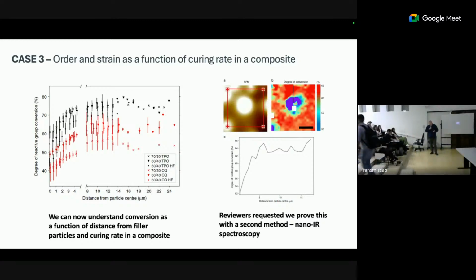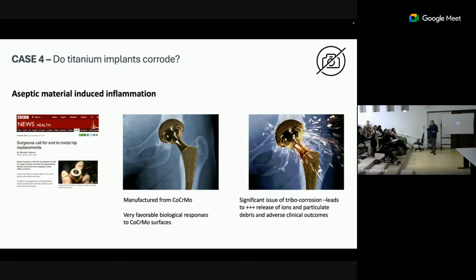On the right-hand side is a different type of measurement that the reviewers asked us to do, which is something that you don't necessarily do at a synchrotron, although you can, which is now called nano-IR spectroscopy. And it gets across something that we know as the diffraction limit in infrared spectroscopy by using a different form where you take an AFM tip, you put the AFM tip on the polymer, you shine mid-infrared light to the base of the AFM tip, and then the surface slightly moves because it's expanding from absorption, and you can generate spectra indirectly. And we managed to demonstrate exactly the same effect on a single particle. So that was the first work I ever did on a composite, and it went into Nature Comms at the end of 2019, beginning of 2020. All made because of access to a different way of measuring.